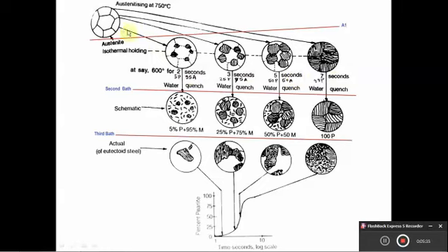So when the sample is dipped from the first bath to the second bath, only 5% of pearlite will transform and 95% of untransformed austenite will remain. Then when the second sample is dipped, it is for 3 seconds, so the percentage of pearlite will increase, so it will transform to 25% pearlite and 75% will remain as untransformed austenite.